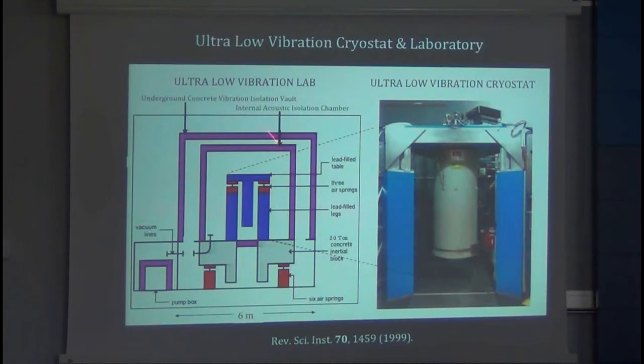And then this vibration isolation table is inside an acoustic isolation room, like a sound recording studio, which is sitting on the foundation, which is sitting on the floor, but the floor is not touching the foundation. It's sitting on vibration isolation springs. So this is like a giant 40-ton laser table, if you're familiar with laser tables. And then this assembly is embedded in an underground reinforced concrete isolation chamber. So this is really a Russian doll design. You just keep suppressing the vibrations until they're gone. The last step is to cool the STM from room temperature down to sub-Kelvin temperatures to get rid of kT.